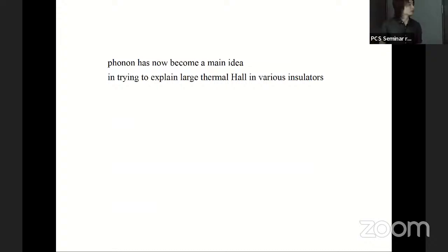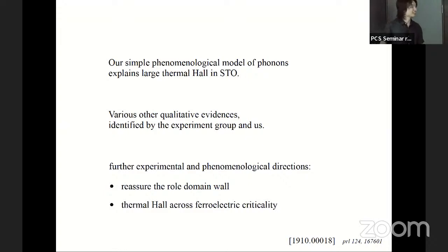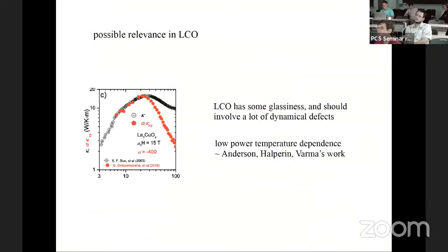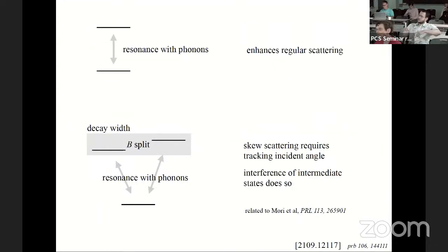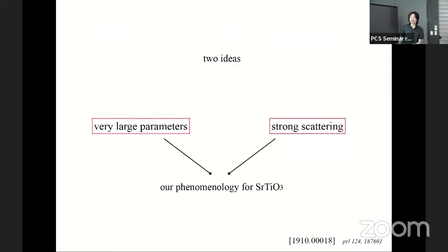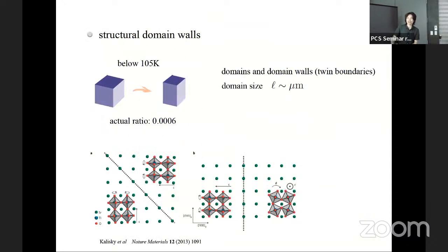Okay, sorry, another stupid question. No, it's just to discuss. So if you apply an electric field from the very beginning and cool down your sample, you will be left without the scattering mechanism. And at the end of the day, there won't be any effect. It's very simple to check experimentally. This is still paraelectric. I apply an electric field, and then I have one domain in my sample. No, the domain is not the ferroelectric domain, it's the structural domain. Structural domain. Right, now I see. Oh, sorry, I thought it's just the ferroelectric domains. No, the domains are like the cubic lattice becomes longer in one direction. It's independent from ferroelectricity. Right.